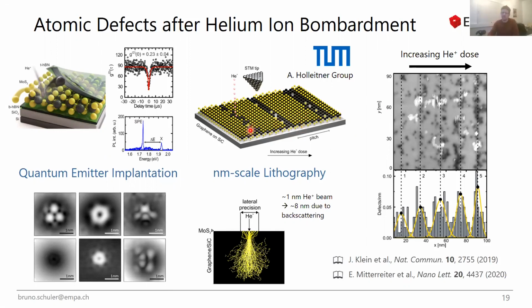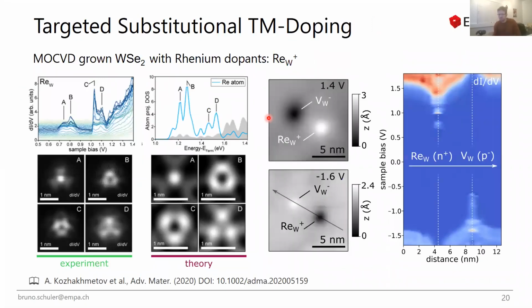So we see sulfur. So that's actually a top one, and that's a bottom sulfur vacancy, among other things. I think the scattering cross section might be pretty similar between top and bottom, so there shouldn't be too big of a difference. But it's quite a bit higher than if you compare it to a transition metal. So forming a transition metal vacancy, it's much harder for the helium ions. All right. Yeah, thanks. So we see both things again.